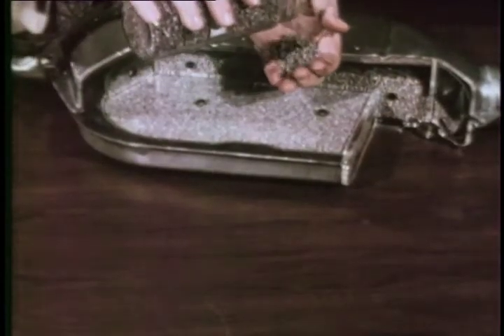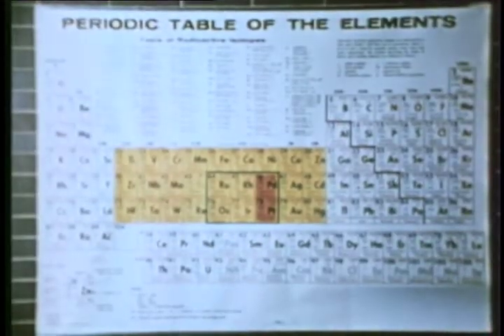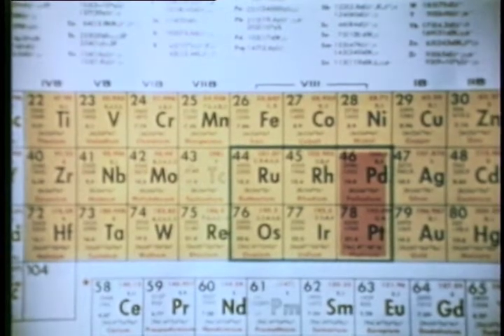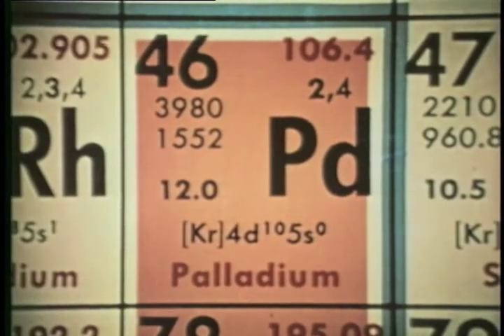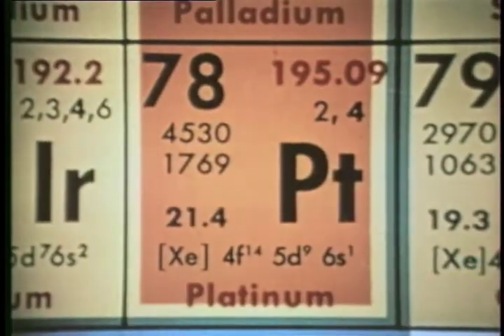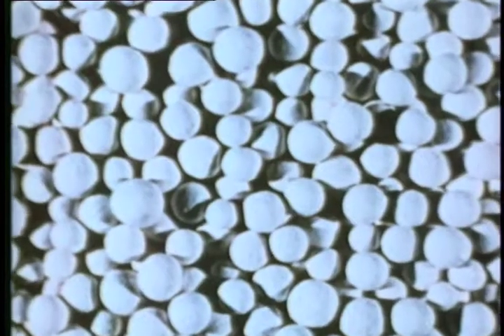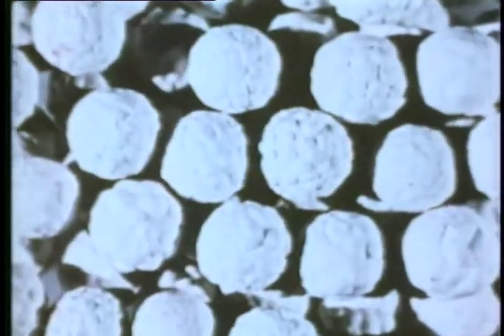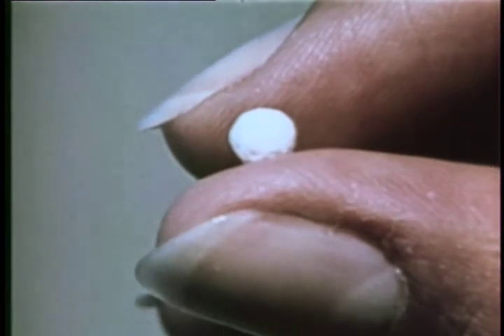The catalyst itself can be either spherical or cylindrical in shape. Both types of substrate are constructed of alumina and coated with a platinum-palladium catalyst. Few chemical elements have the type of catalytic activity required. These elements are generally in the middle of the periodic table and many are rare precious metals such as platinum and palladium. Current statutory emission level requirements necessitated using the most active and durable catalysts available. It was determined through experimentation that base metal catalyst formulations such as copper and chrome would be intolerant to contamination from sulfur found in petroleum, and base metal catalysts do not reach peak operating efficiencies as quickly as those made from noble metals. Noble metals are also less sensitive to lead contamination.